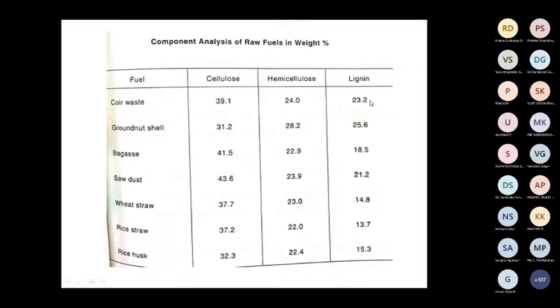Lignin also is 25.6% in the groundnut shell. In other things, straw fuels, we have 13 to 14%, 15% lignin content. So groundnut shell alone is having some peculiar characteristics: the highest hemicellulose and high lignin content. This is the one observation I could make. Groundnut shell.